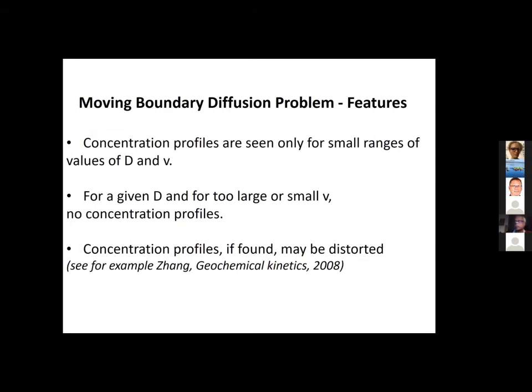But then the question is, how do you model that one? Because the concentration profiles can get a little distorted. So that's something we need to worry about. And then we need to sort of know what this V is. And that is the problem, because actually doing the calculation is difficult, but doable. The problem is knowing how fast or slow things are growing and dissolving. But if you see a step profile or if you see a sharp boundary, that does not mean there was no diffusion. So that's the message I wanted to give you.